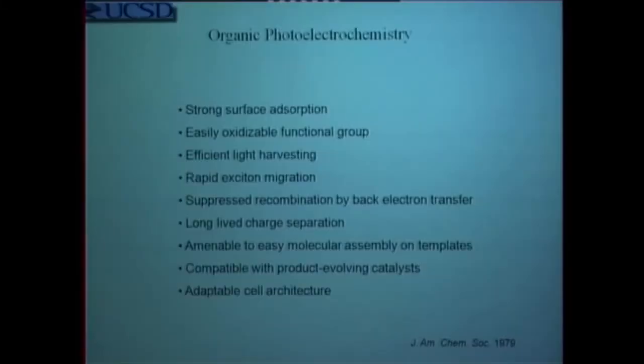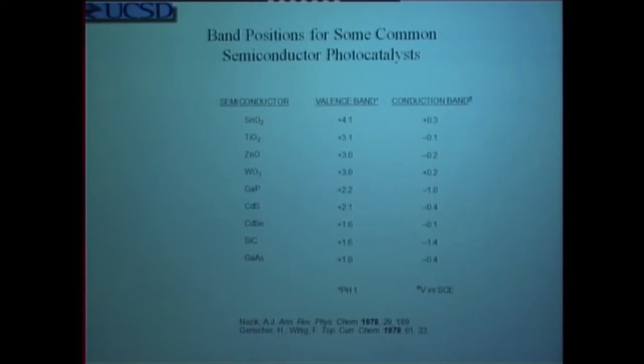Excitons can split and opposite charges can migrate in different directions, and we can suppress recombination by using the surface to attempt to control back electron transfer. This creates very long-lived charge separation, which is amenable to assembly on templates. And to the extent that we're able to manipulate the size and surface of the titanium dioxide particle, we have an architecture which would be ideal for controlled oxidation and reduction reactions. Now, when I say control reactions, basically what I'm talking about is having a potential which is greater than the oxidation potential of the compound that will induce an electron to be lost and the molecule will be oxidized. So here, for example, are some potentials just chosen routinely to show you exactly what kind of band positions we're talking about.